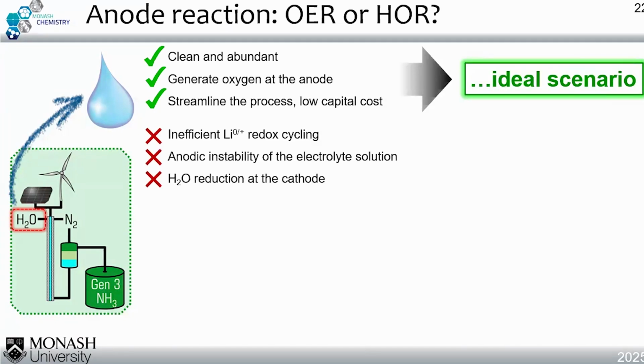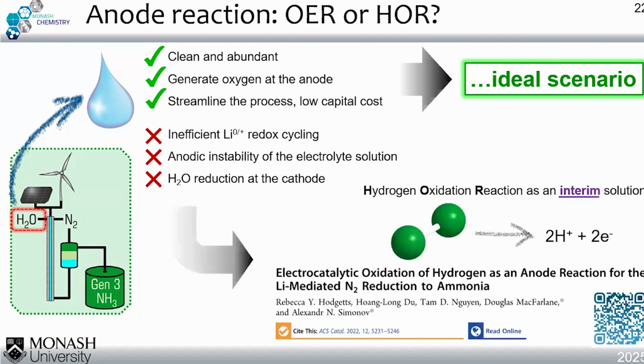However, lithium and water don't like each other. So if you introduce water in the system of lithium NRR, you actually reduce the lithium redox cycling. And when the water and the organic solvent cross over, you actually stop the activity in both anode and cathode. So we propose the interim solution, which is a hydrogen oxidation reaction. So hydrogen can actually be obtained from water electrolysis, which is the intermediate process.